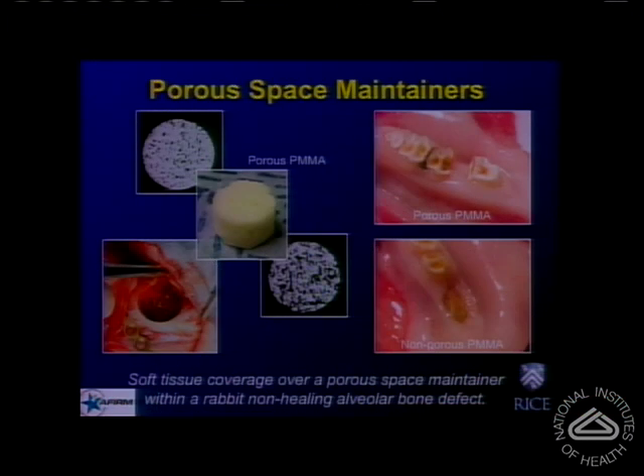What is very appealing to us about using porous polymethylmethacrylate is that, in addition to the enhanced soft tissue healing, one can use this material in a porous form to deliver antibiotics. Using non-porous polymethylmethacrylate, because of the hydrophobicity of the polymer, any antibiotic loaded within the polymer remains within the bulk of the polymer, and only a very small fraction is released to the surrounding medium. Having a porous matrix, we can release most of the antibiotics to the surrounding tissue.